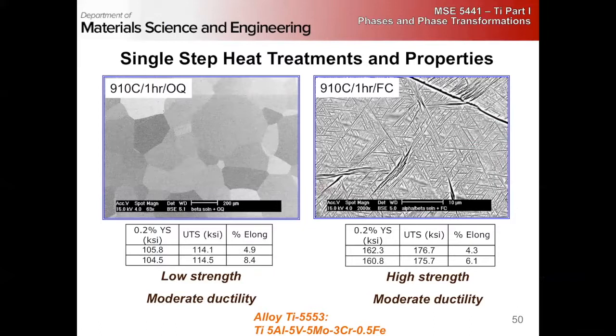And we want to pay attention to the general properties here. This is going to be low in strength and have reasonable ductility. This is going to be higher in strength, also have a slightly reduced but also decent ductility. Unfortunately, these are in KSI because these came from GE slides, so just pay attention to that. The actual value is not really of concern to me. It's just the general trends.